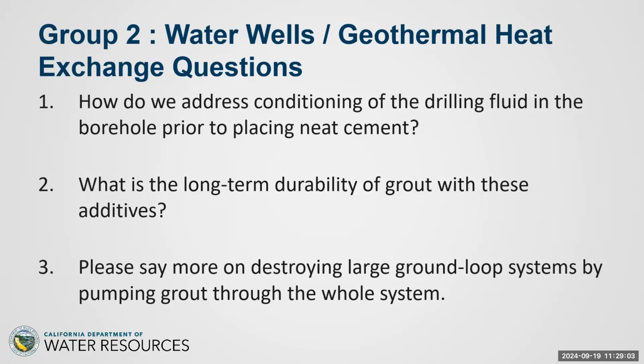The only thing to watch then is with the bentonite, if you use excessive bentonite, and so we build some cutoffs with self-hardening drill slurry and stuff like that, as you folks know. If the water content of these mixes is extremely high, the cement content is low, and the bentonite content is high, then there is the danger of a long-term durability aspect, just because of desiccation. Simple as that. And the grout gets spongy and crumbly. The same way as if we use sodium silicate to try and accelerate the set of the grout, if we use too much of that, the grout will get spongy and will crumble. So in most of our HMGs, or high mobility grouts, no long-term effect with the use of these admixtures or additives, none.